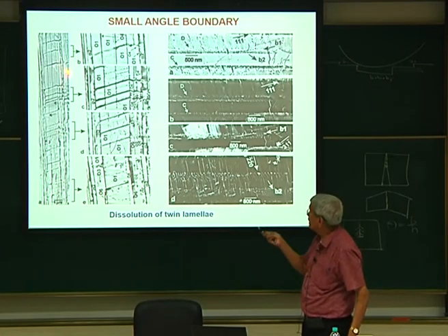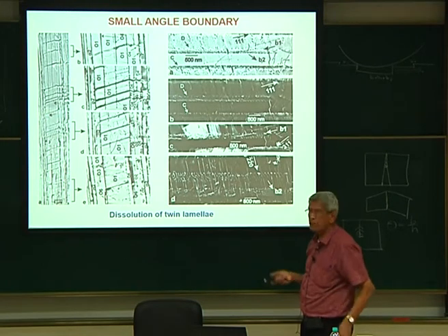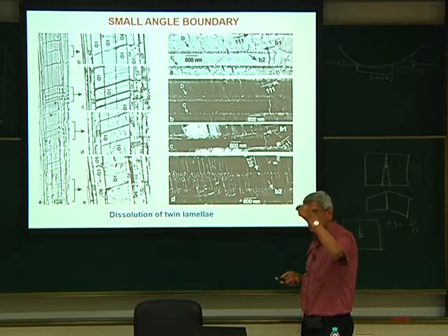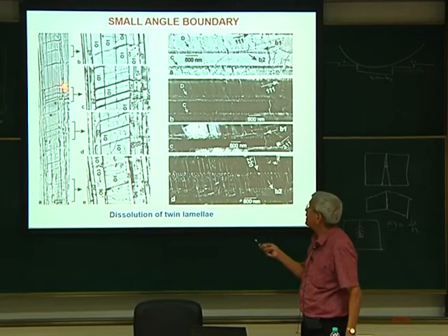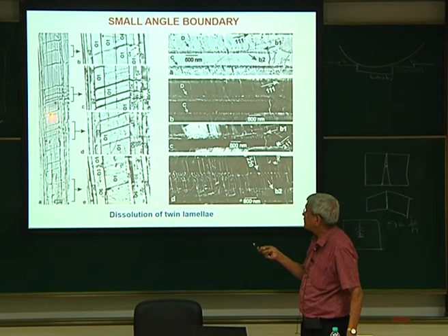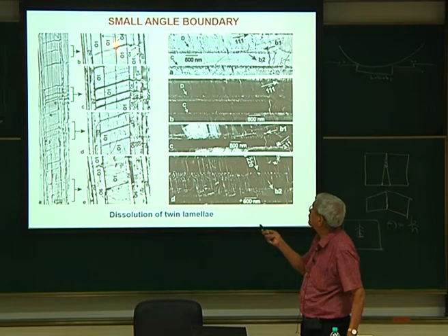Similarly, this is another case in this alloy. What is happening is that a very small twin layer, an ordered layer, has formed, and that ordered layer is receding. When it is receding, because of the strains present around the twin, one can see a lot of dislocations. In this picture you can't see it, but in the magnified view these are all the twin region taken from this region. In this region where the twin has tapered, it has almost come to an end.